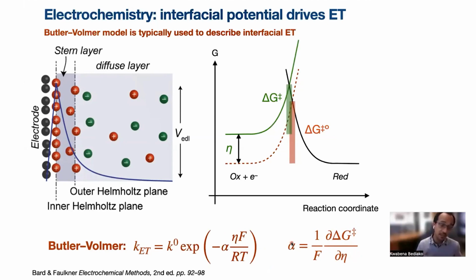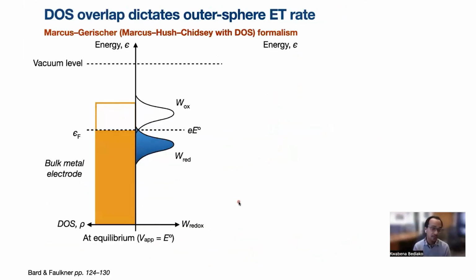And it also is actually very limited in describing cases where the electrode electronic structure, the density of states, is not necessarily constant as a function of energy. And so instead, we need to think a little bit differently, using Gerischer's formalism or the Marcus-Hush-Chidsey model, which describes the rate of electron transfer in terms of the electronic density of states of the electrode and the probability distribution function of the solution redox couple. So you could think of this as the HOMO-LUMO levels of the molecule in solution.